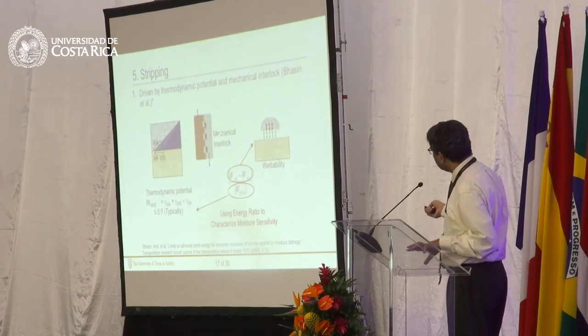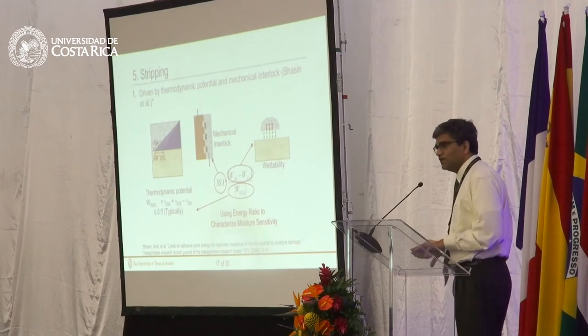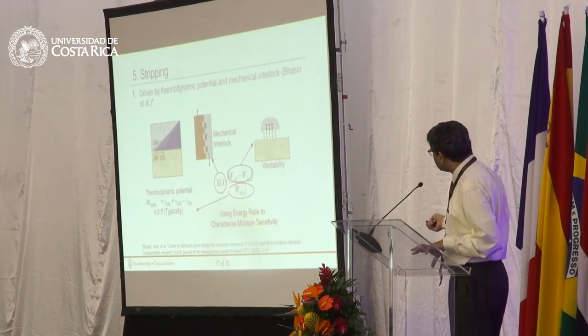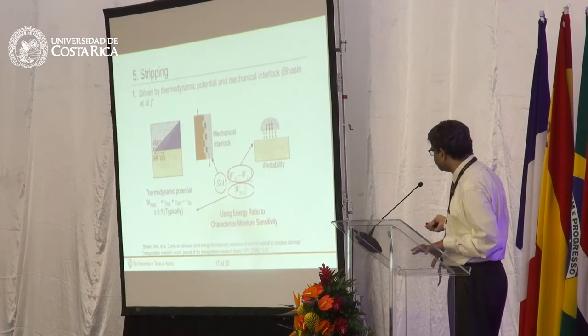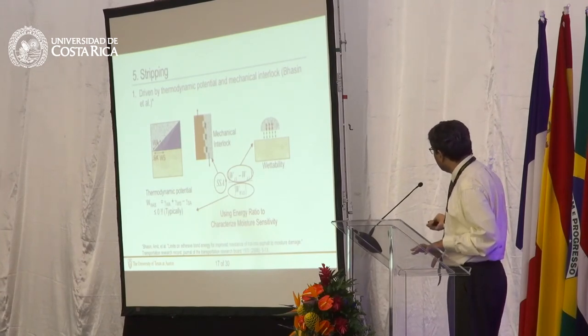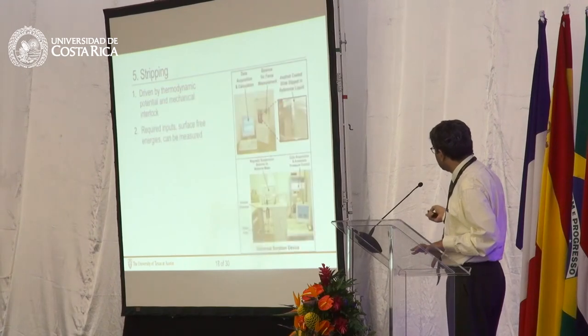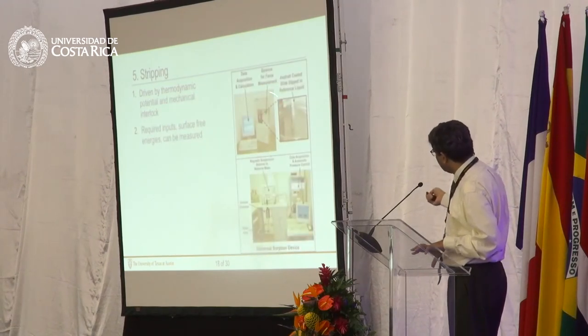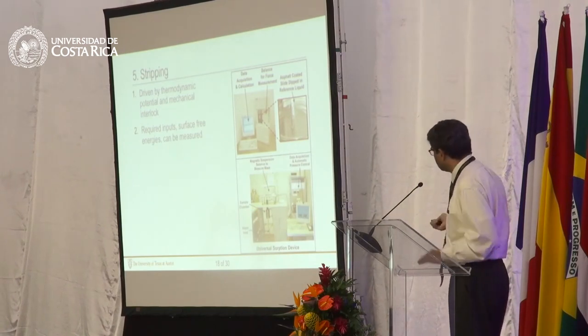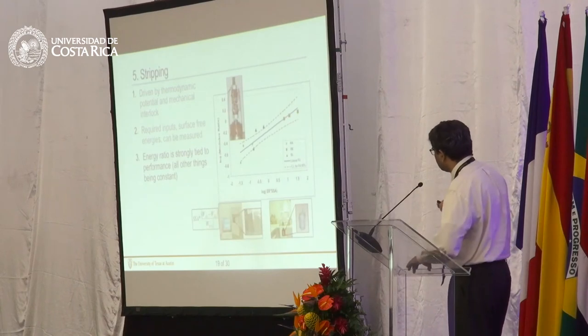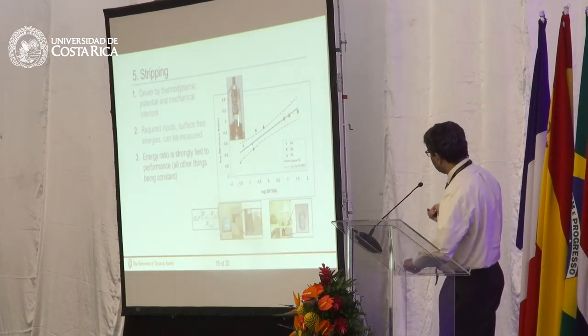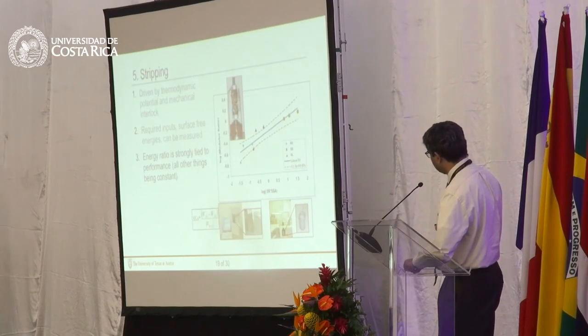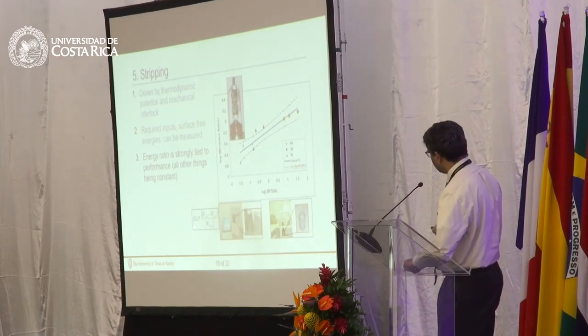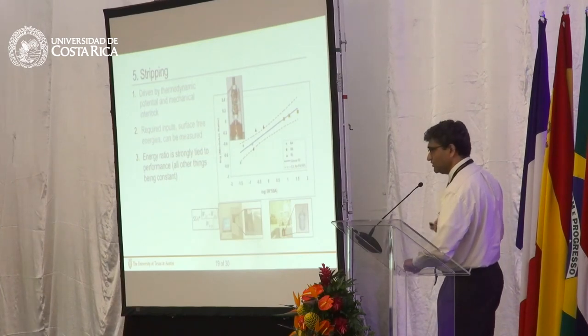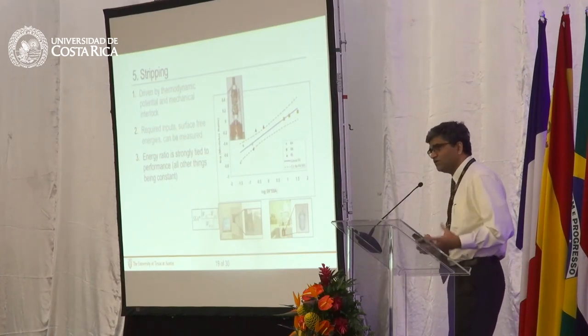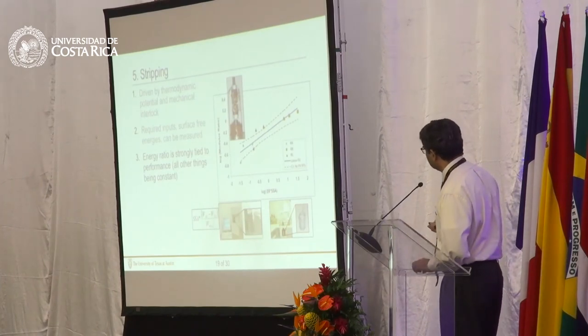And then we also looked at the mechanical interlock effect, which is captured by the specific surface area of the aggregate. So this is purely based on thermodynamics. This is purely based on mechanical interlock. And if you look at this energy ratio parameter, we've done carefully controlled studies. These are just two devices, the Wilhelmy plate device and the sorption device, that can be used to measure these parameters. In some of the studies that we did, we have shown that if you look at mechanical tests of carefully controlled specimens and look at this energy ratio, you'd see that there's a strong correlation between the two, meaning you can tell when the materials are not compatible by running these surface energy measurements.